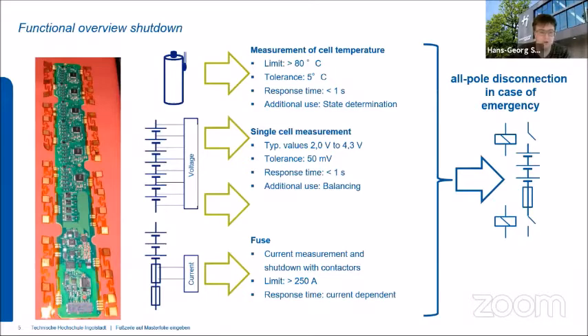From the voltage point of view, it's strongly dependent on the cell chemistry you use. So if you design a battery system, you must be aware of the specific voltage range of the cells you use, because the lithium-ion cell is not a lithium-ion cell, because you can use different anode and cathode materials there, and so they have different voltage limits. So you have to check for the individual voltage limits of the specific cell you use in your battery system. Typically, you have an overvoltage limit in the range from 4.2 to 4.3 volts, and a lower voltage limit something between 2.5 down to 2 volts. Tolerance and response time here do not need to be super quick, because it takes its time and you have to overcharge a lot until a battery cell reacts in a nasty way.